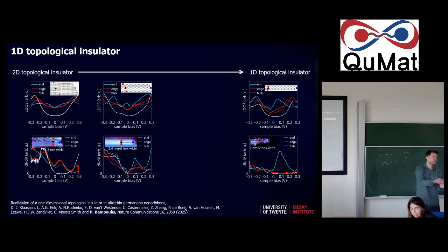And also you have to engineer it so that it's in segments, right? The growth that we do is just, the widths that we get are all random, right? And then we just look and start with the ones that we have. I think it's already a challenge to have the same width everywhere in the nanoribbon, but that you go from 3 to 2 to 3, that's an even bigger challenge. But something like this they have done for graphene nanoribbons, and they have started to follow that. Yeah.